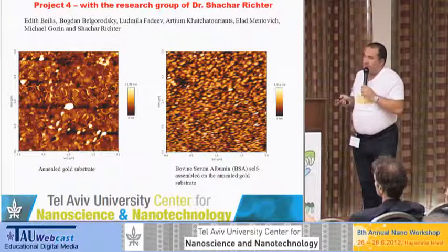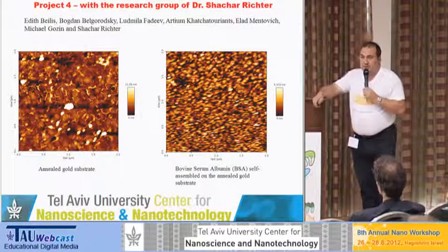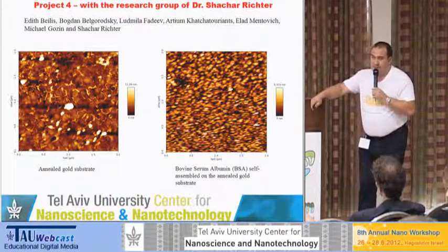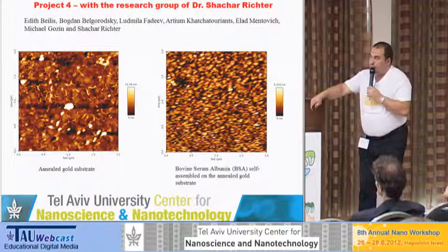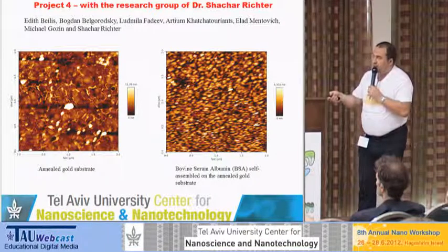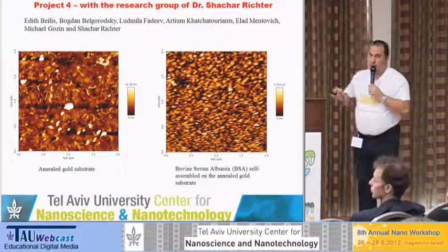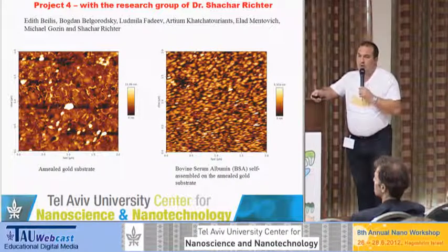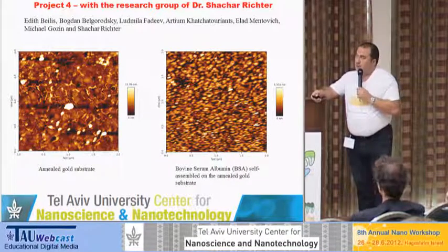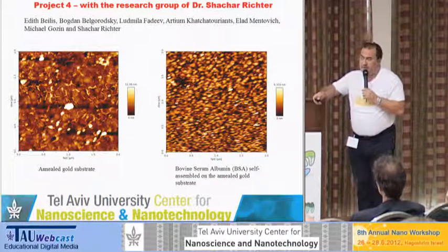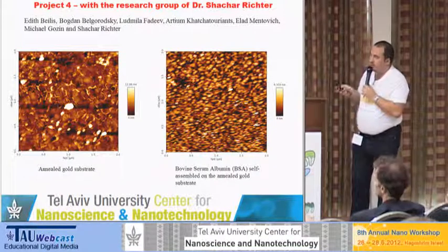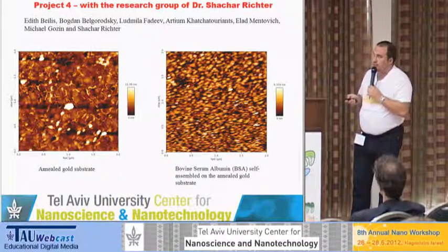Such self-assembled monolayers on gold possess interesting optical properties in the range from UV to near IR. So it is of importance to characterize such surfaces. Here you see the AFM image of the annealed gold. If you just coat the silicon wafer with gold, you will see something like that. It will be like a granulated structure. So in order to make it flat, you need to anneal it.